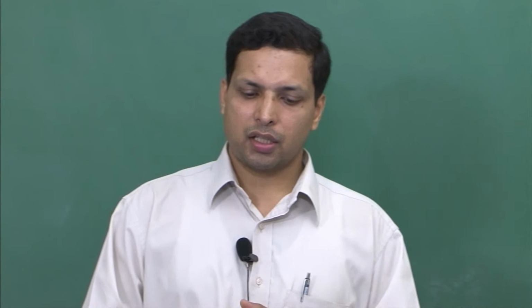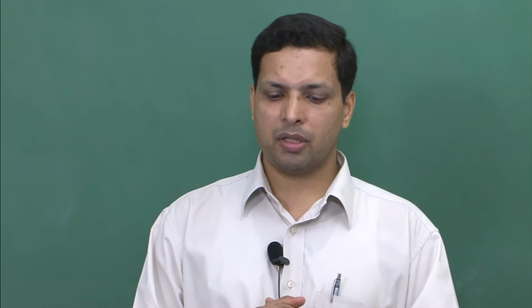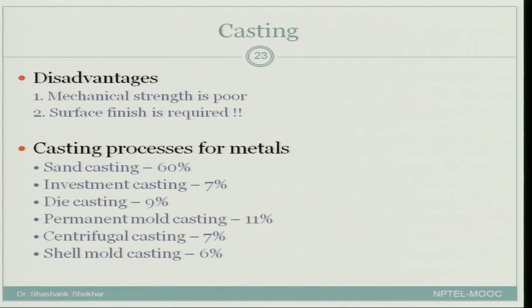Now there are also some disadvantages for casting. One of them is that mechanical strength is poor. Why is the mechanical strength poor? Because the microstructures that form are very inhomogeneous. Near the surface, like even in the first example that I showed you, you get a chilled zone, and inside you get some columnar zones, and therefore the microstructure is not so homogeneous, and so you get not so good strength. And like I said, surface finish is also a disadvantage, because in most of the basic casting techniques like sand mold casting, you will require some amount of surface finishing to be able to use it as a component.